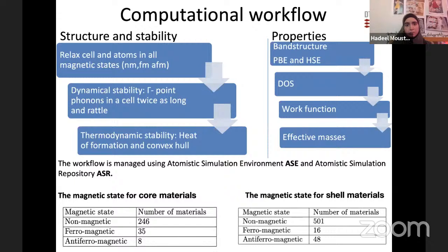So for both the core and the shell materials, here is our computational workflow, which has 2 parts. The first part is the structure and the stability, and the second part is the properties. For the structure and the stability, we start by making a relaxation of the cell and the atoms in all the magnetic states. And here we see the magnetic state for the core materials. As we can see, almost all of them are non-magnetic, and some of them are ferromagnetic, and a few of them are antiferromagnetic. For the shell materials, almost all of them again are non-magnetic, but now more of the materials are antiferromagnetic compared to the ferromagnetic.